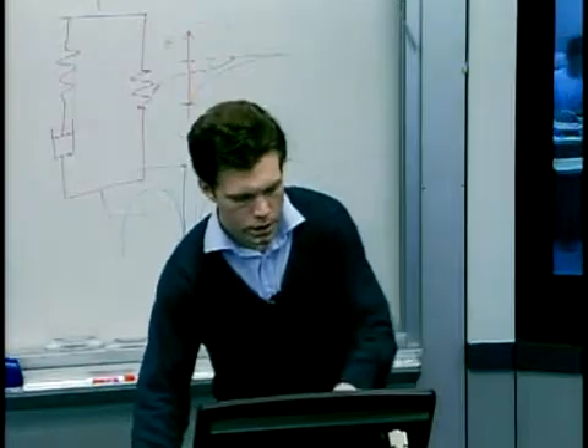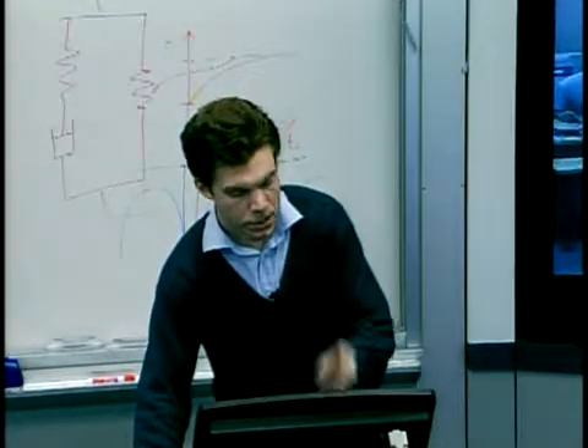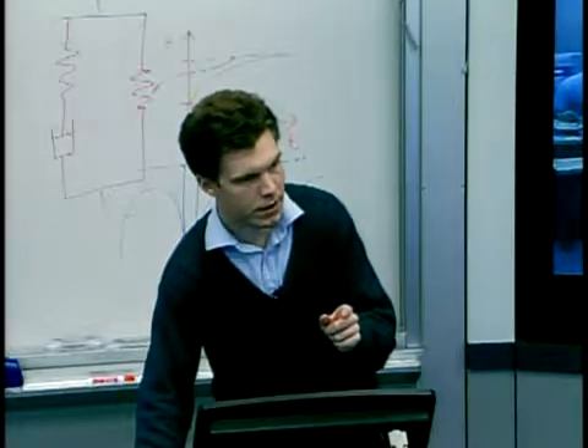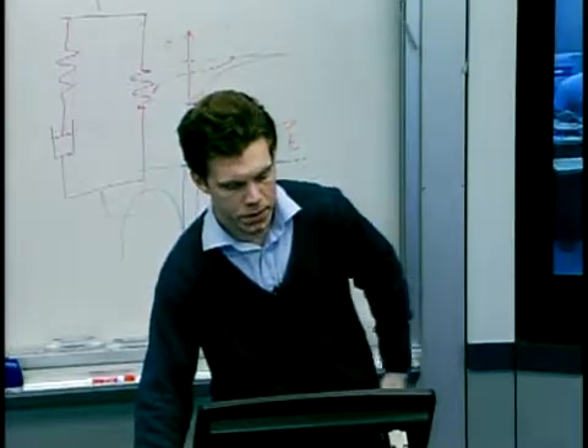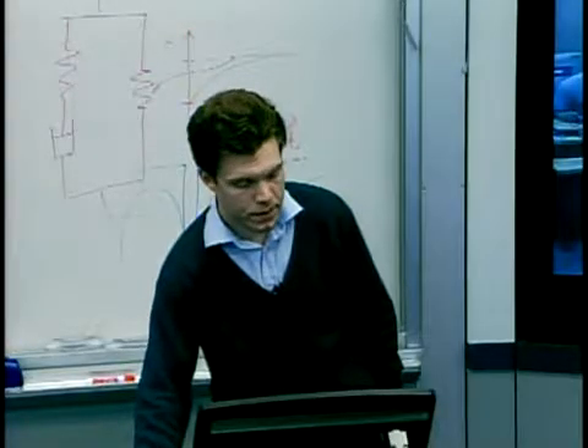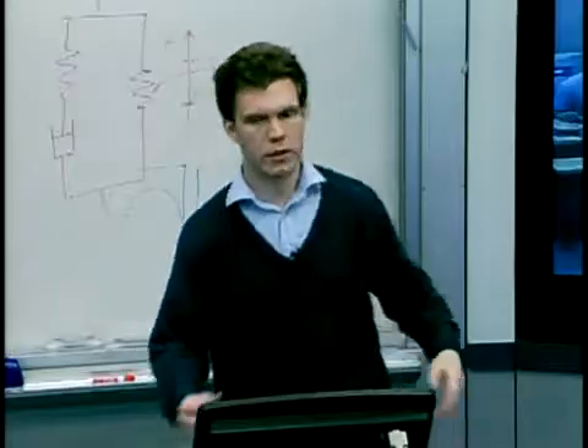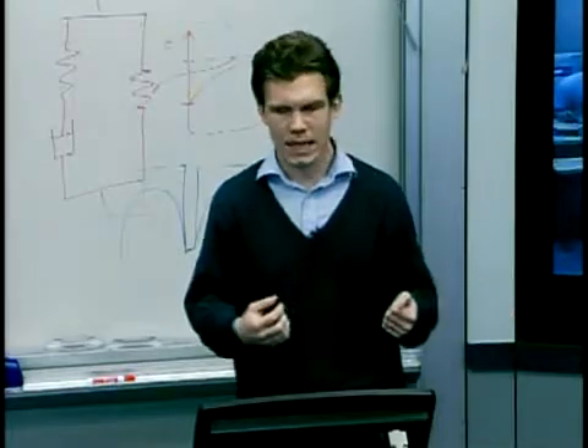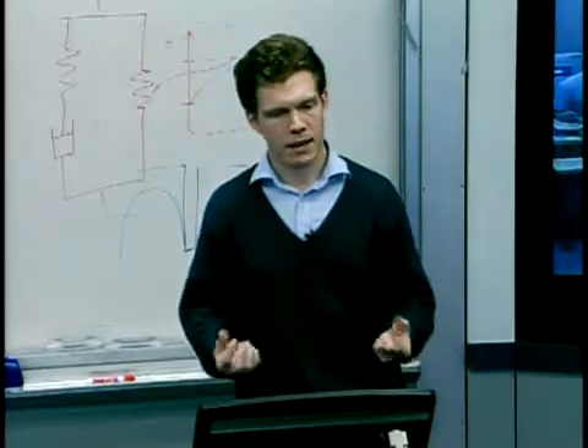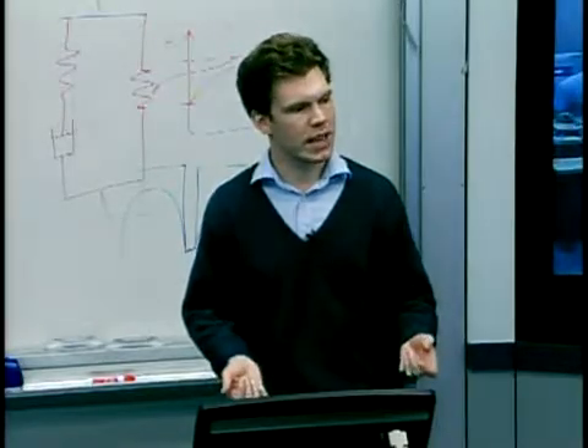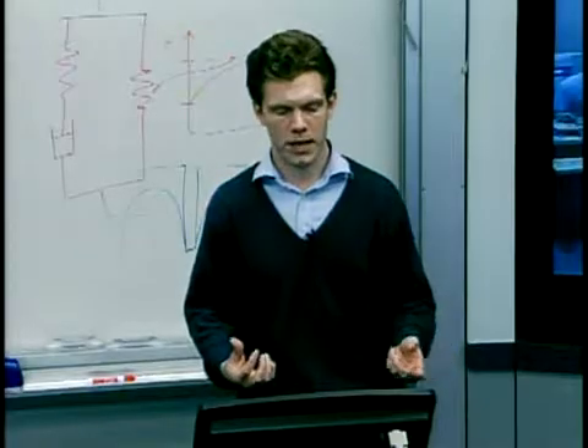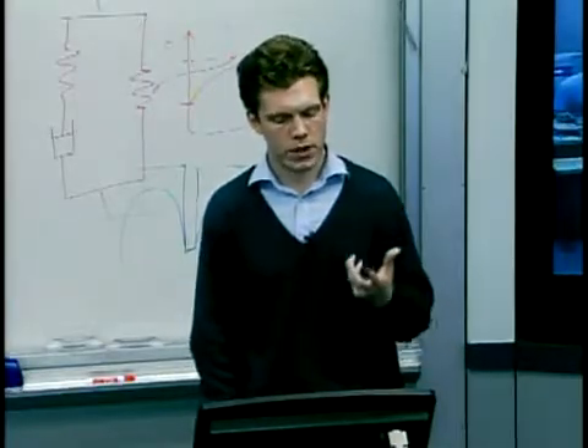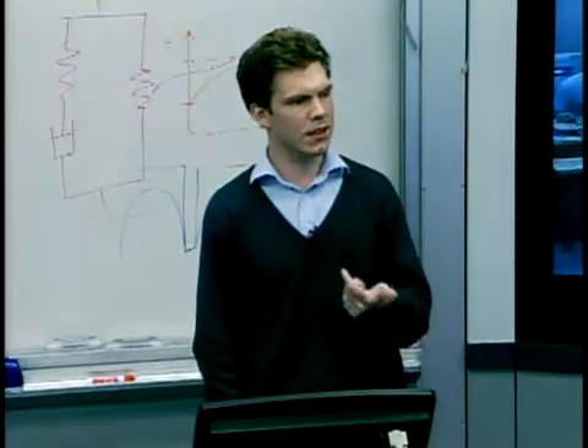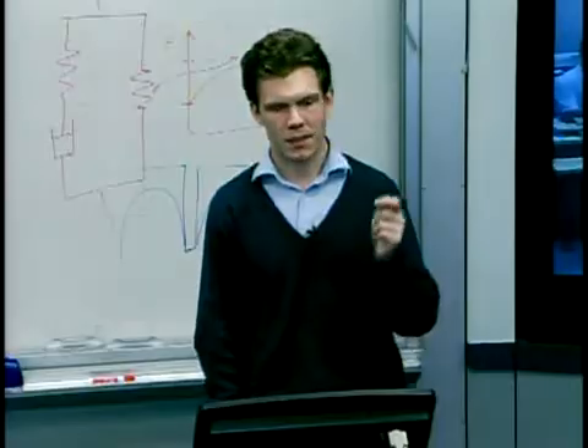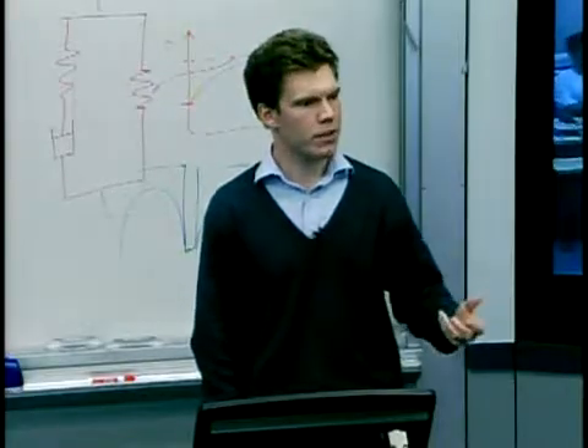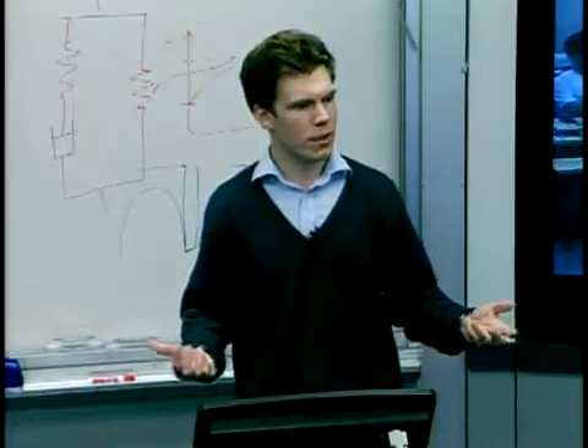And these results are based on 5 replicates. You can see the error bars there, 1 standard deviation of the 5 replicate results. And there's definitely a significant anisotropy, whether that's to do with residual stress in the cast sheets, or alignment of the polymer chains because of some feature of its processing. I mean, you can start to see that if materials like this have such a big orientation dependence, and that is so dependent on how they've been processed, you can't necessarily know the whole processing history of what you're supplied.